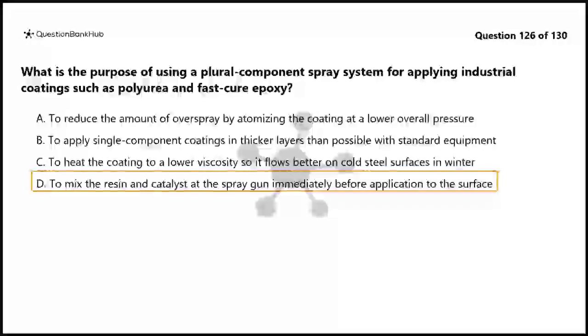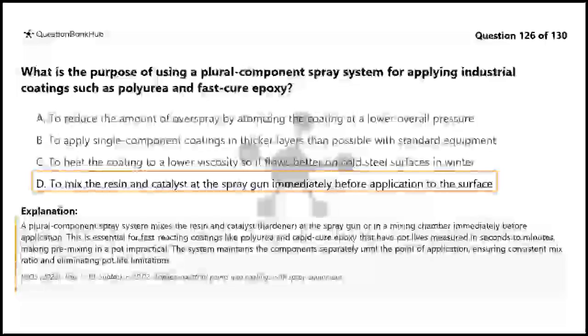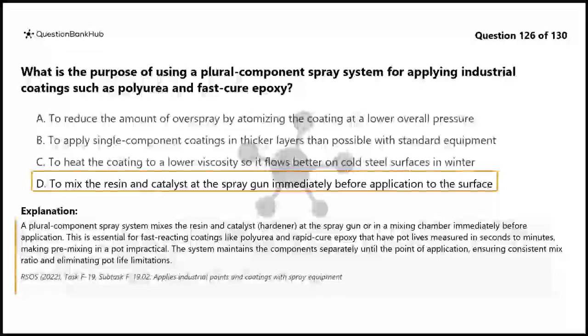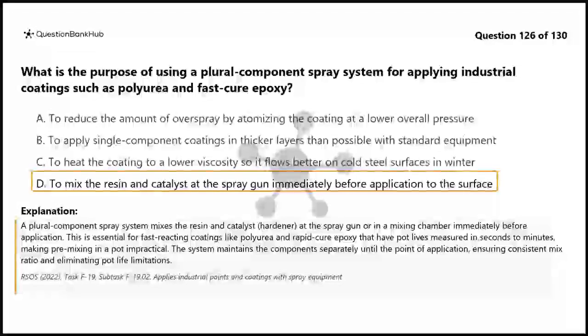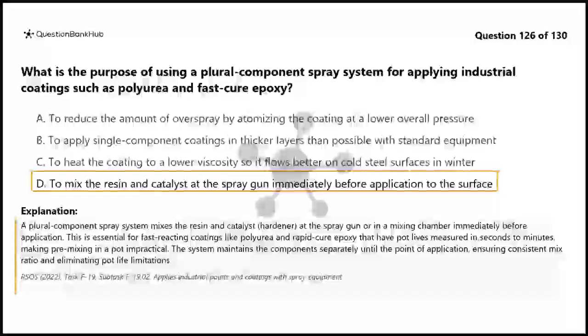The correct answer is D. A plural component spray system mixes the resin and catalyst, hardener, at the spray gun or in a mixing chamber immediately before application. This is essential for fast-reacting coatings like polyurea and rapid cure epoxy that have pot lives measured in seconds to minutes, making pre-mixing in a pot impractical. The system maintains the components separately until the point of application, ensuring consistent mix ratio and eliminating pot life limitations.